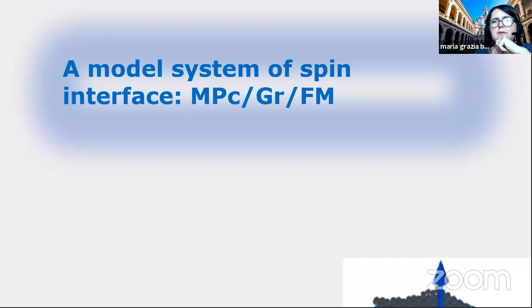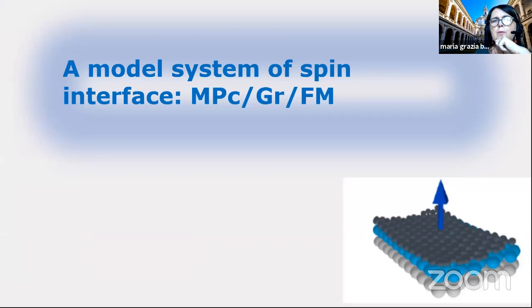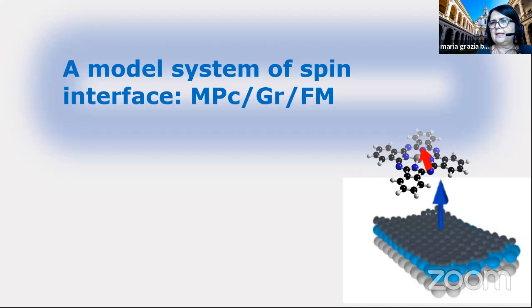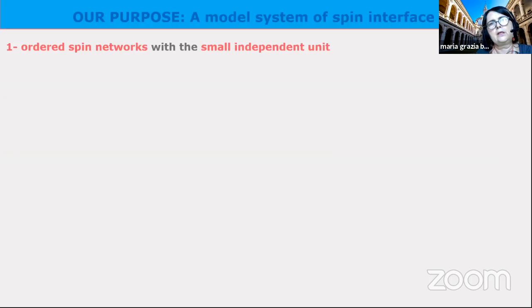So we were thinking to propose a system of spin interface where we can preserve the magnetic moment of the molecule, and then we can couple this magnetic moment with a ferromagnetic substrate. And we propose a model like this.